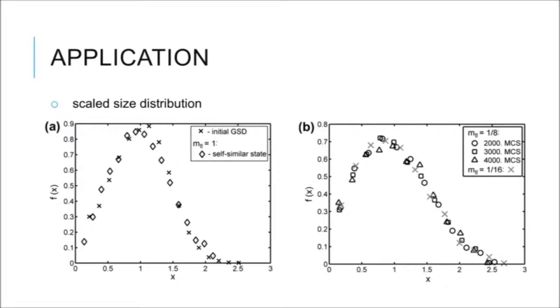Apparently, it's shifted to smaller relative grain sizes, meaning we have more grains with relatively small size. In addition, it also has a slight tail, so basically we do have grains that are 2.5, 2.6 times the average size. So the distribution becomes broader and slightly skewed.